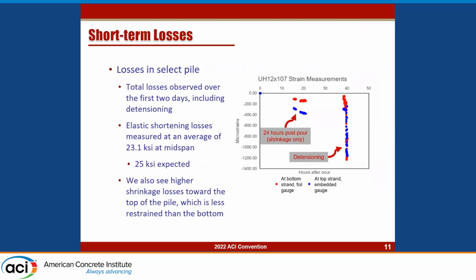Now, regarding our short-term losses, we looked at all of our data from before the pour, the next day, and then during detensioning. Based on first principle calculations, we expected elastic shortening losses of 25 KSI, and we got elastic shortening losses of about 23.1 KSI. So we were very close on that. Those calculations matched pretty well to what we saw in the field. We also saw some higher shrinkage losses towards the top of the pile, which is less restrained than the bottom.